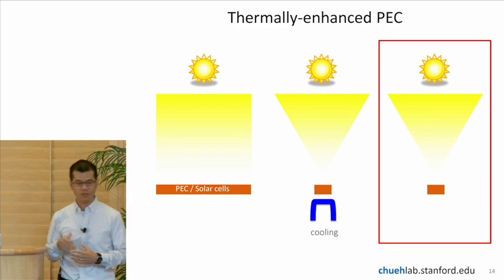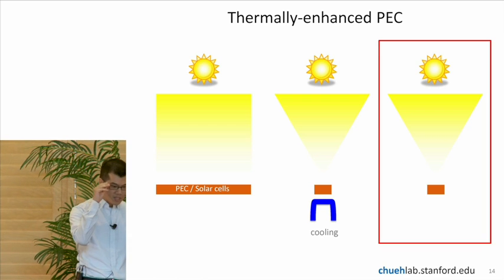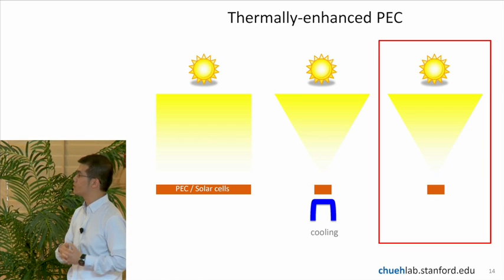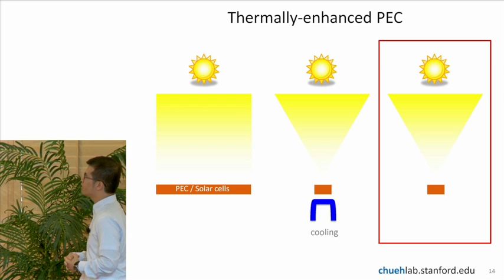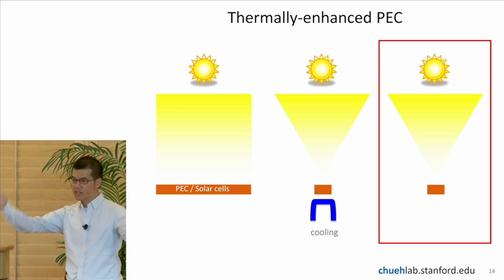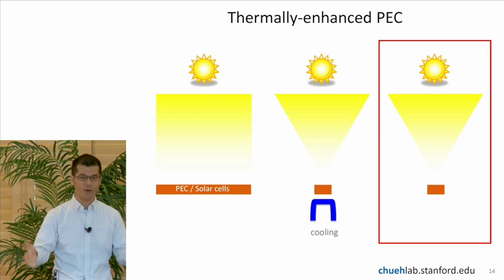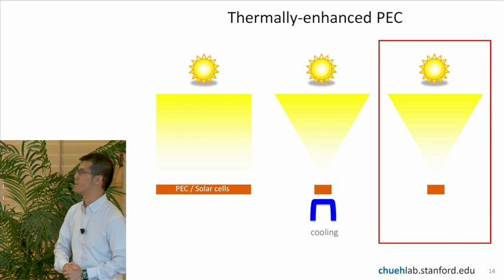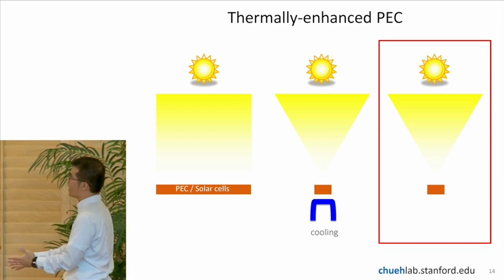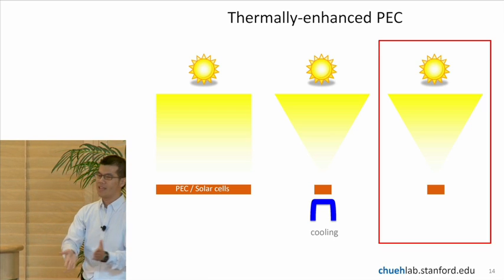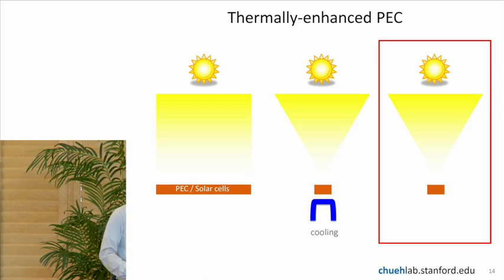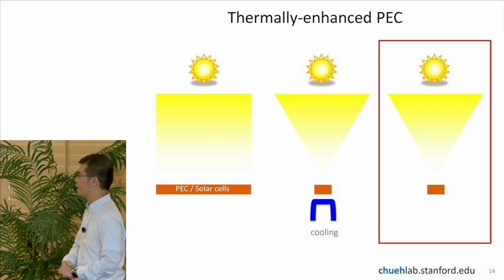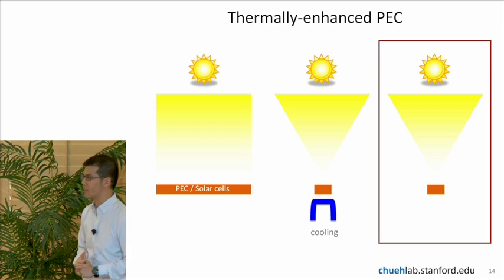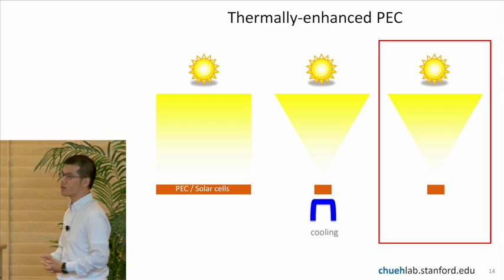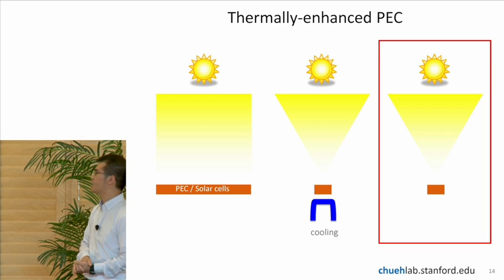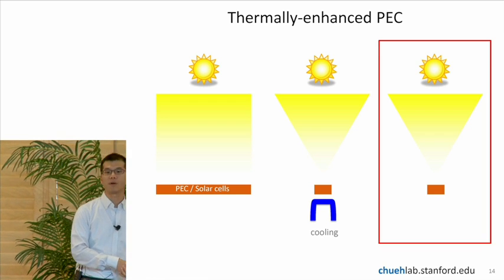So if I were to summarize the results so far, the concept of a thermally enhanced photoelectrochemical cell is appealing to us because of the following. On the left, you have the standard case of non-concentrated light hitting a photoelectrochemical cell or solar cell. So this is the baseline case. One possibility in the second case is you can concentrate the light, but in the case of a solar cell, you usually have to cool the solar cell because the power output of the solar cell decreases. So you have to have active cooling. This has been a challenge with the field of concentrated photovoltaics because of the expenses associated with cooling and system complexity.